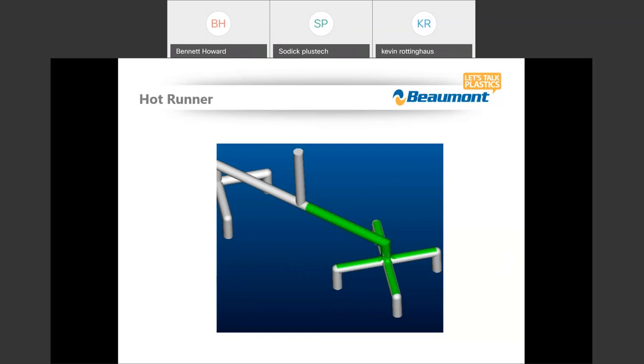Years ago, some students at Penn State Behrend in the plastics program there built a mold that had no end of fill. A better way of explaining it, it had a sprue and a runner that just wrapped around in the mold and then just vented out of the parting line of the tool. They built a little beaker that they were able to stick underneath the mold with a very long handle, and they shot plastic in at different melt temperatures. They did different types of polymers, and they did different fill rates.